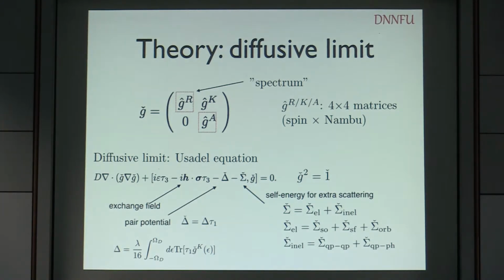You have already seen the Usadel equation in this meeting several times. We can write the Usadel equation for this, since typically the systems that we are studying are in the diffusive limit. They are disordered. So this Green's function satisfies this equation, and then what we need to add are the relevant parts describing our setup. Besides just the energy, which is the Fourier transform of the time derivative, this term here is the exchange field that we might have in the system, and this is the superconducting pair potential, which satisfies a self-consistency equation.